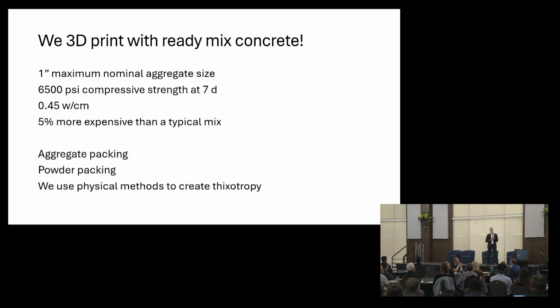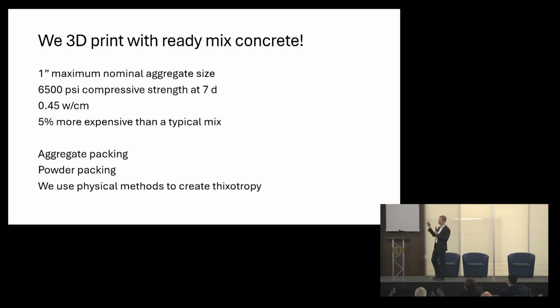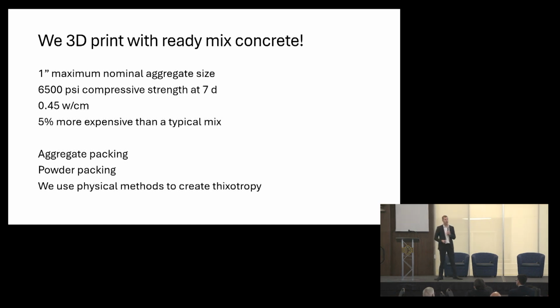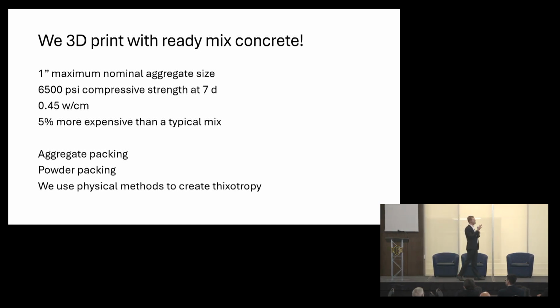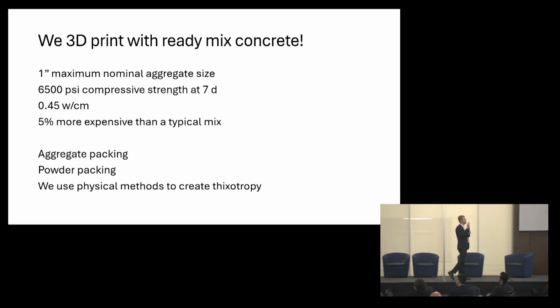So we make our concrete do this. But our concrete, we use 1-inch maximum nominal size aggregate. So large rocks, all right? Our concrete has 6,500 PSI compressive strength at 7 days. We're not designing for that high strength; that comes along for the ride. We use a 0.45 water-cement ratio. Our mix is about 5% more costly than a typical mix.